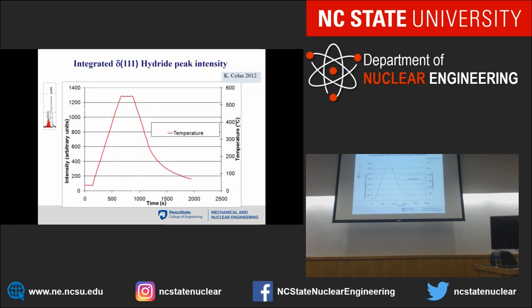So here is a typical experiment. We have integrated hydride peak intensity. So here's the temperature profile. Start at room temperature, go up. This is that height here. I have about 500, and then I cool down, right? So now I have a sample that has 500 weight ppm, let's say.